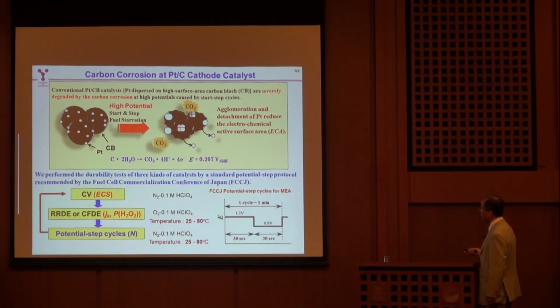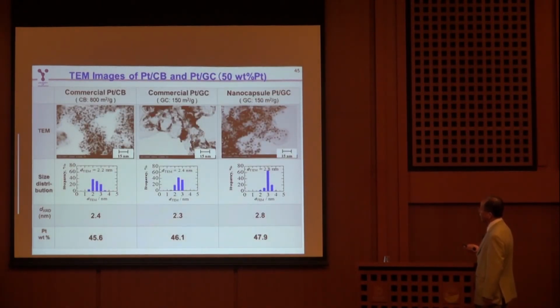So here we tested our catalyst in comparison with the commercial catalyst by using the start and stop cycle, simulating potential cycling shown here: 0.3 volt for 30 seconds and 0.9 volt for 30 seconds, repeating these cycles on each catalyst, and measuring the specific surface area and also the catalytic activity for the oxygen reduction reaction at room temperature to 80 degrees Celsius. Here we show the catalyst TEM images and size distribution of the commercial carbon black supported catalyst, the graphitized carbon support catalyst, and the nanocapsule catalyst.